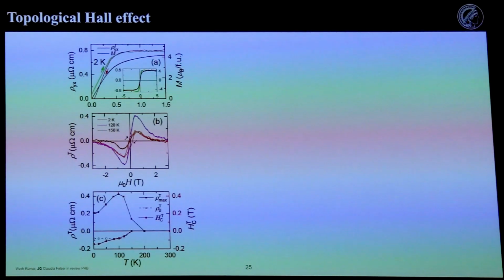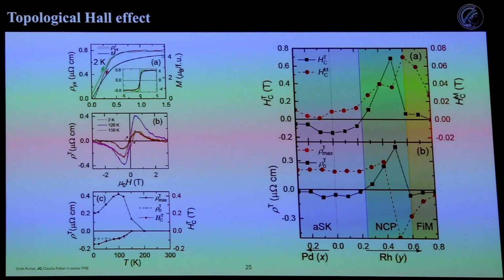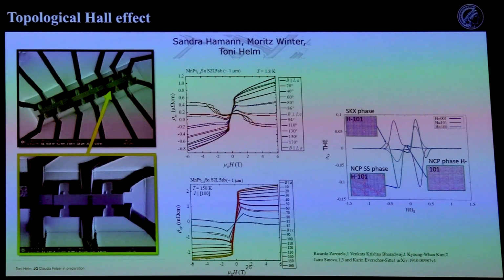We continue with these compounds and did many other cases, and from these transport dynamics, we can point to, okay, if you have an anti-Skyrmion phase, as you put palladium or rhodium in, or a non-coplanar phase, or a ferromagnetic phase. And this is really just playing with the transport, if it aligns with the magnetization or not. To continue, and then, this is almost to the end.